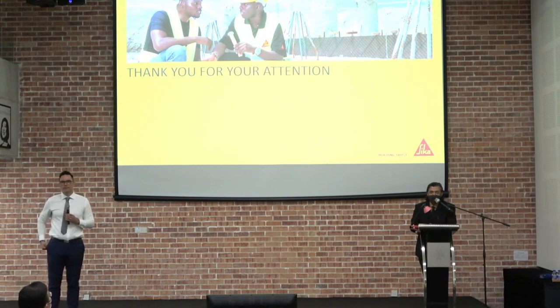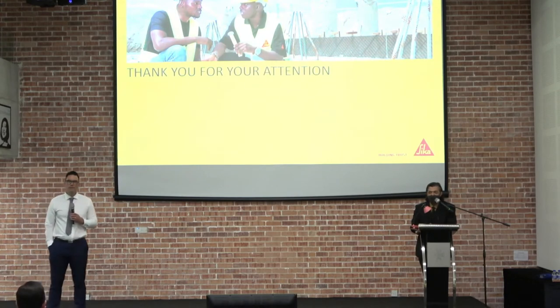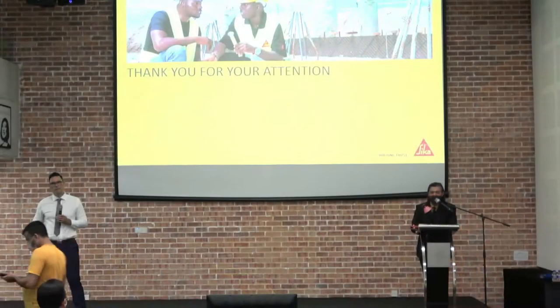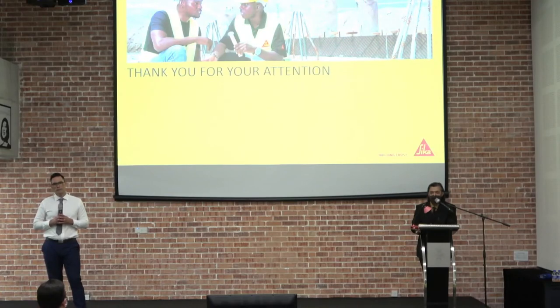I've used quite extensively the Sikaplan PVC membrane on concrete roof, flat roof with a very low gradient. The material performed well. The drawback is the surface protective screed that we have to put on top, that maybe within the first year they are in place, second year, you will notice the surface of the protective screed showing stress, crack. But down there, the PVC Sikaplan is okay, it's intact.